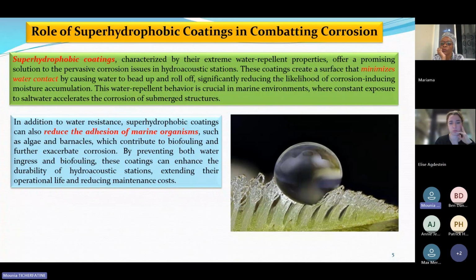Indeed, this water-repellent behavior is crucial in marine environment, where constant exposure to salt water accelerates the corrosion of submerged structures. In addition to water resistance, superhydrophobic coatings can also reduce the adhesion of marine organisms, such as barnacles, which contribute to biofouling and further exacerbate this corrosion. So by preventing both water ingress and biofouling, these coatings can enhance the durability of hydroacoustic stations, extending their operational life and reducing maintenance costs.